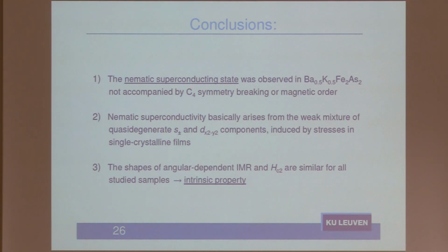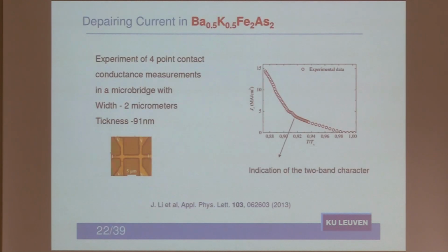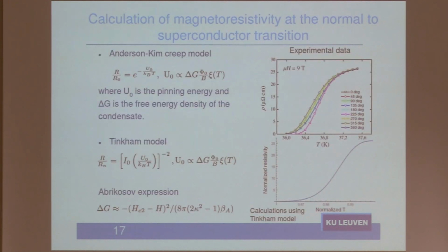Can I simply, very naively, say that the main idea is that you have superconductivity of S wave, that is positive, plus D wave, plus and minus. If you put them together, then you have plus lobes which are extended and minus lobes which are removed. Yes, this is the main idea: not C4 but C2.